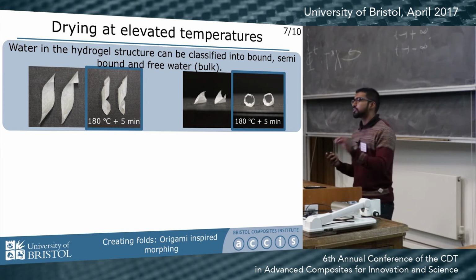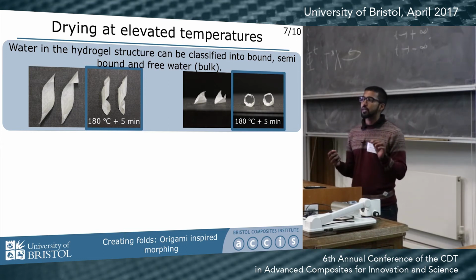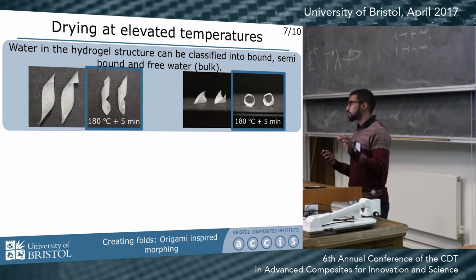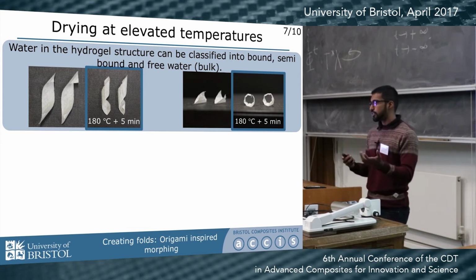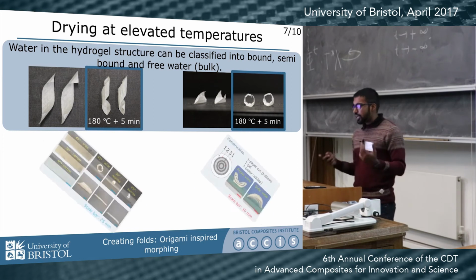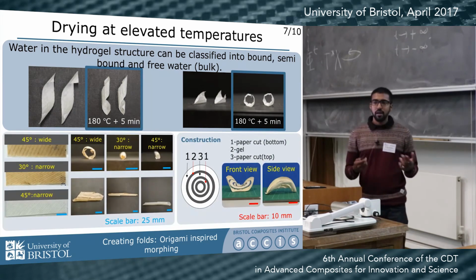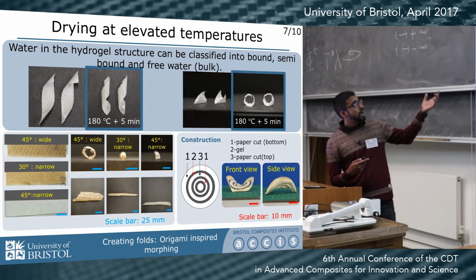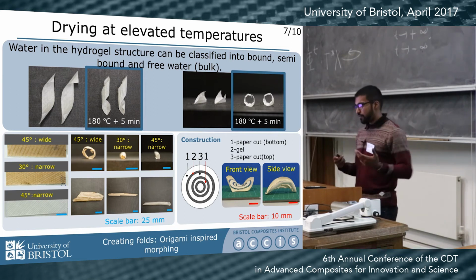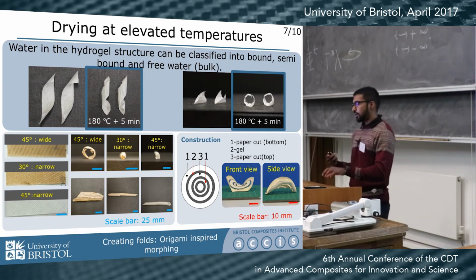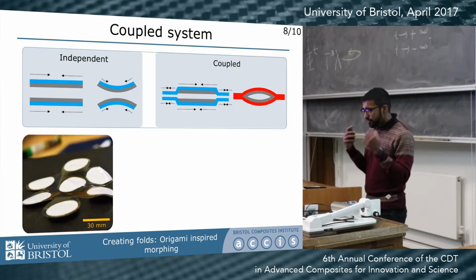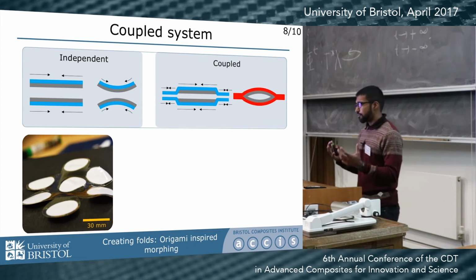The temperature chosen here will also result in self-cross-linking points within the hydrogel, and this is crucial for repeatable actuation of these forms. Shown here are some common origami shapes realized with this method. We have spirals with different chiral parameters and a flat annulus, which is morphed into a saddle-like shape. This methodology is not limited to curves and folds.